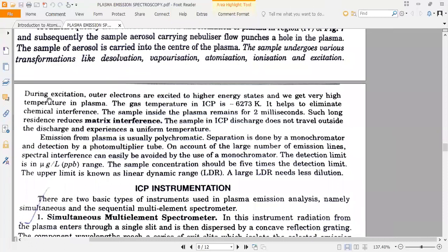You know what happens then? Excitation: outer electrons are excited to a higher energy state, and we get very high temperature in the plasma. The gas temperature in ICP is around 6273 kelvins. It helps to eliminate chemical interferences. So such high temperature is required to remove chemical interference. The sample inside the plasma remains for 2 milliseconds only. Such duration reduces matrix interferences. The sample in ICP discharge does not travel outside the discharge and experiences a uniform temperature.